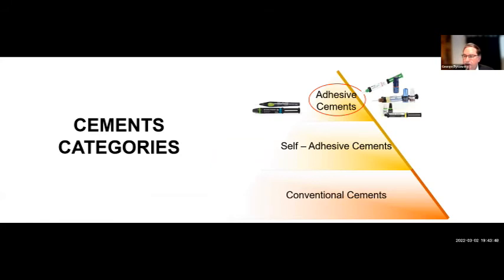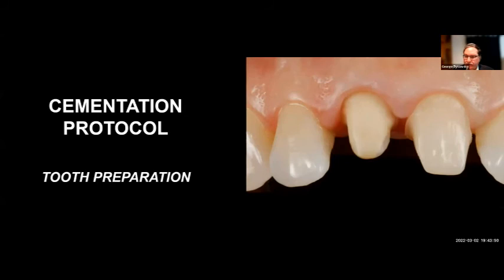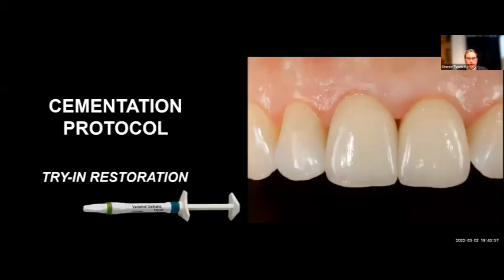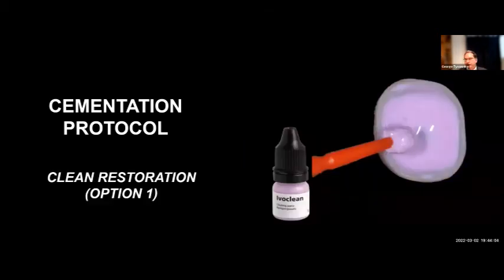And then we can talk about the cementation protocol here for adhesive cements. We're going to bond the restoration in place. So we have a clean tooth structure. We're going to do a try-in. There are try-in pastes available for the composite resin cements. This is our Variolink try-in material. We want to make sure that after try-in, we clean the restoration, and we have the ability of using these phosphate protein cleaners, like IvoClean, and there are other materials available for this process. A very viable material that provides a very clean surface for the internal aspects of the restoration.